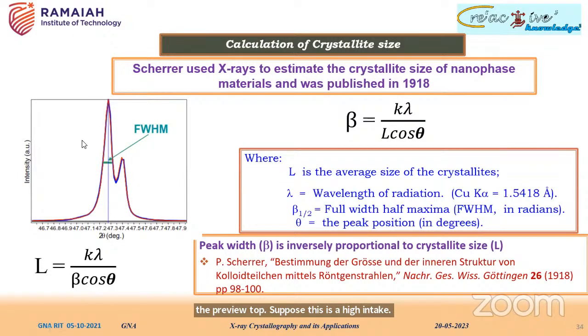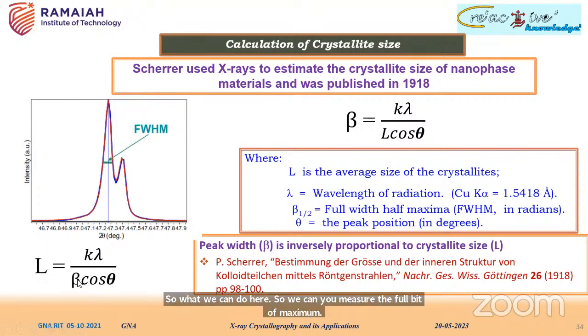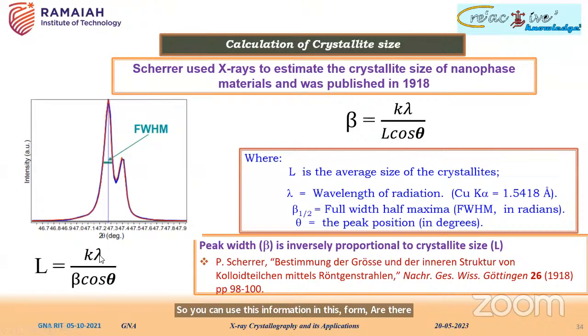So what we can do here is measure the full width at half maximum. You can use this information in this formula, where K is a constant, lambda is the wavelength of radiation used, and theta is the Bragg angle. And by substituting it, you can actually determine the particle size.